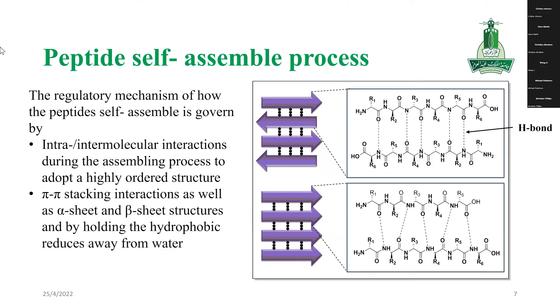Peptides self-assemble due to intra- and intermolecular interactions between different side chains that help give a highly ordered structure. If you have phenylalanine or tyrosine, there is pi-pi stacking between the different aromatic rings. These all move away from water — they are hydrophobic, cluster together, and remove away from water.